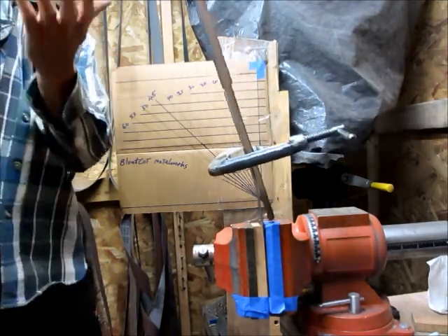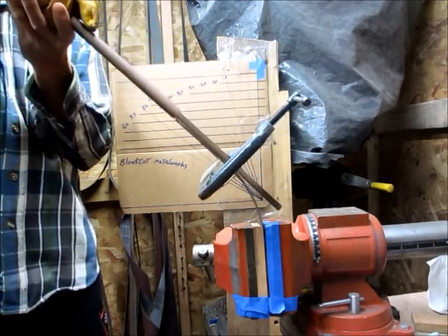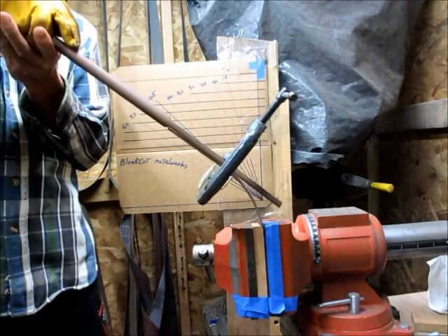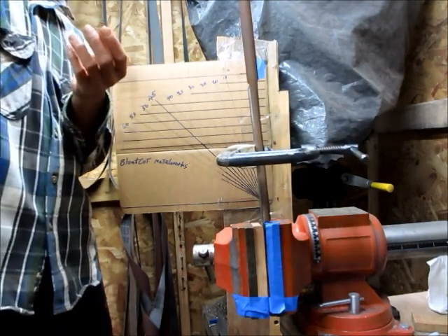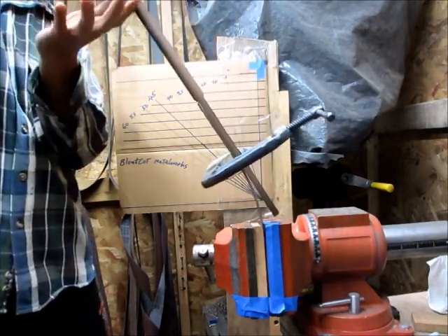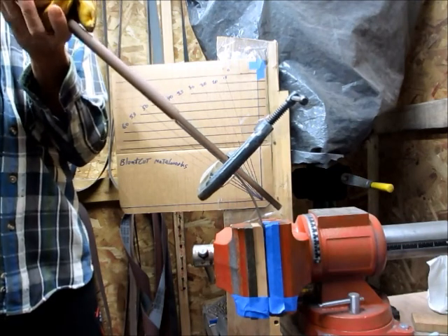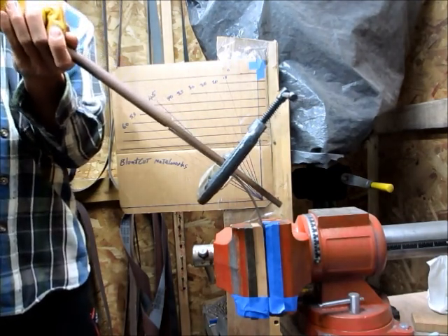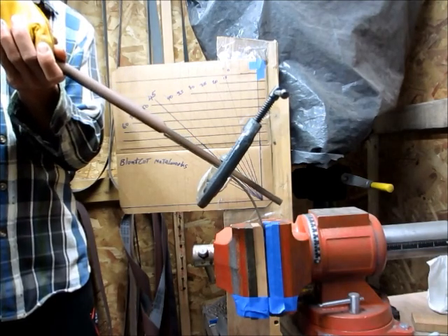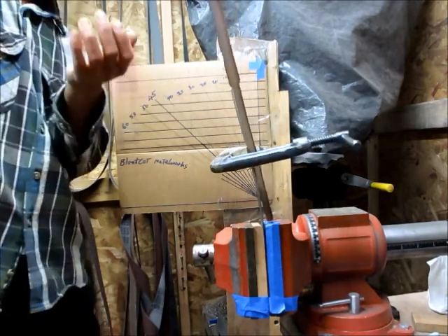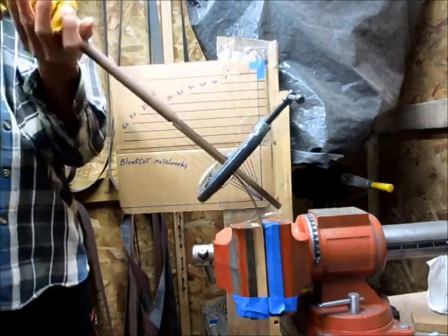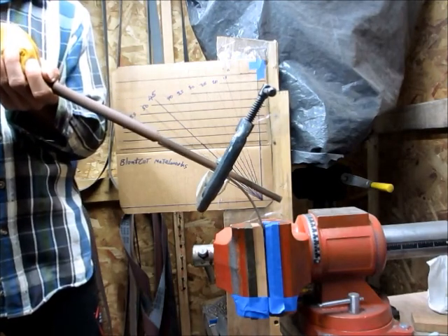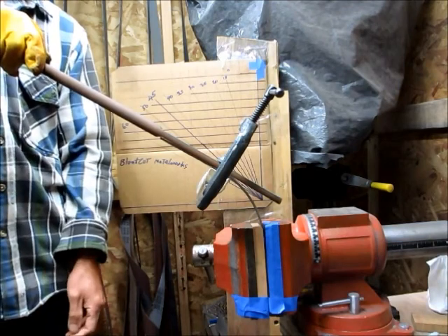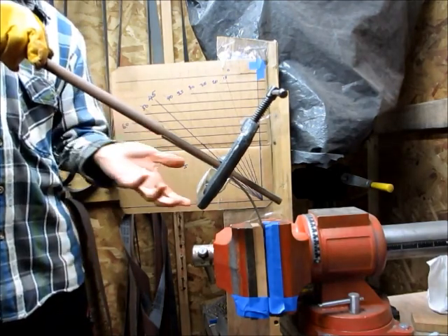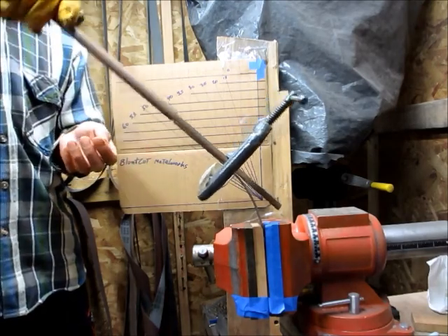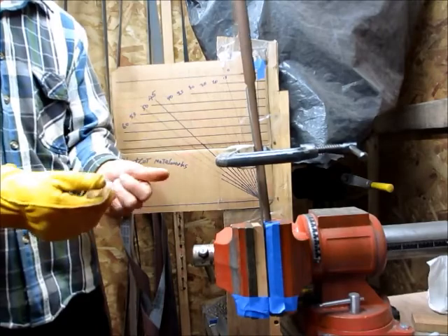well, the 66 bent a lot, so unless there's error, the 64 should bend more. I do find that when I got something like 63, 62, it didn't bend any more than the harder one. So I think that the elastic and the plastic stay fixed until there's enough iron or ferrite to allow it to move, because the stretched end of this bar has to elongate, and at some point they have to move. But if there's not enough to move when you bend it, then it just shatters.